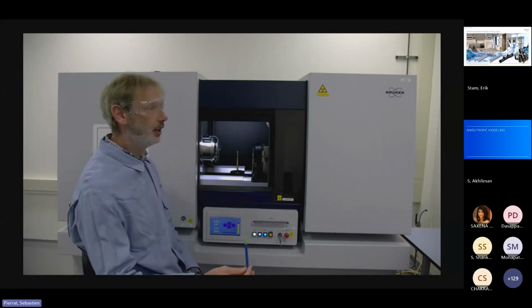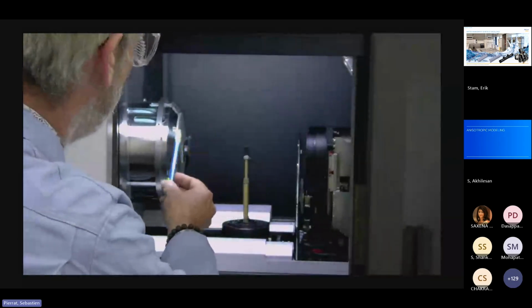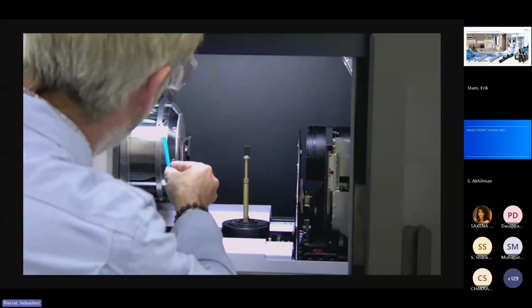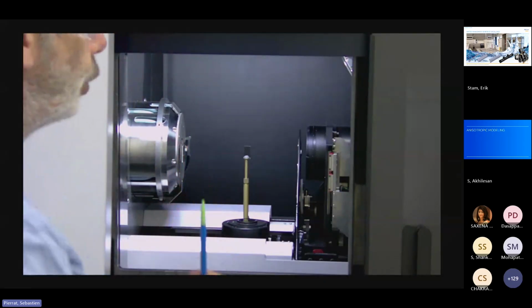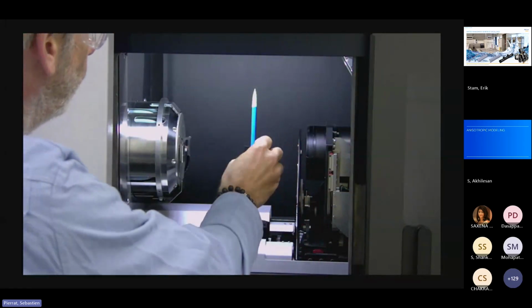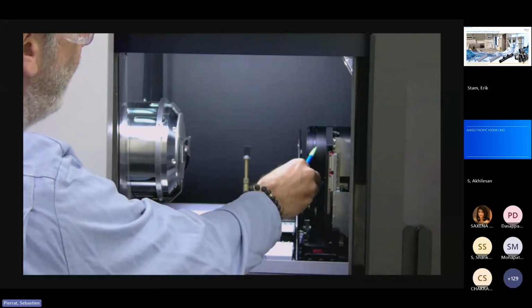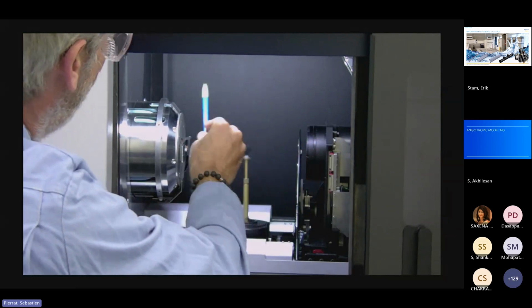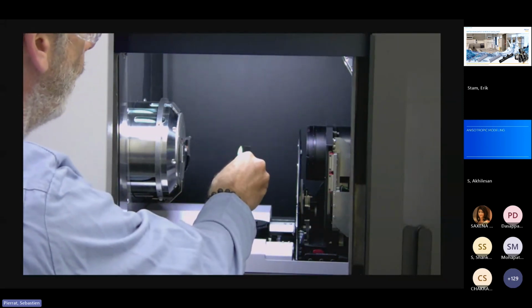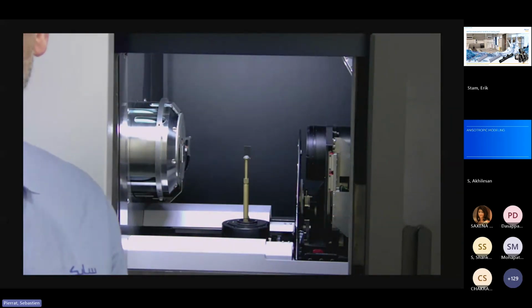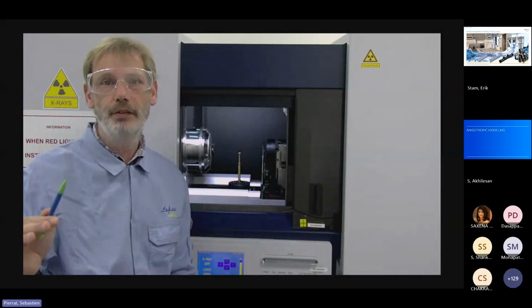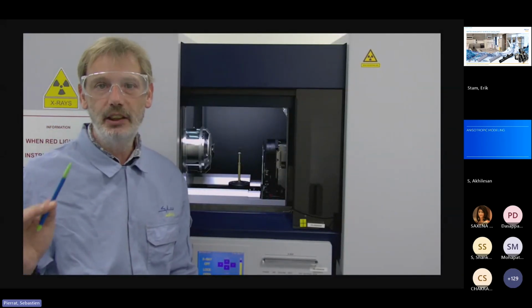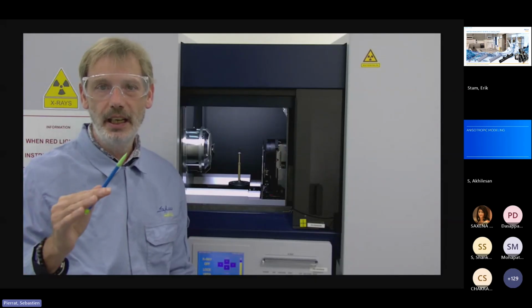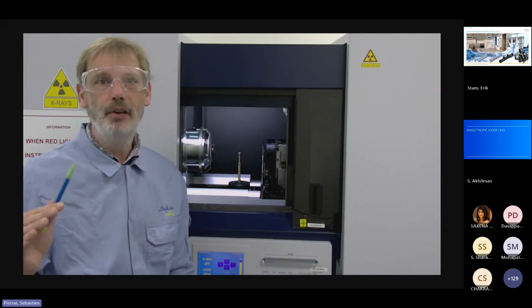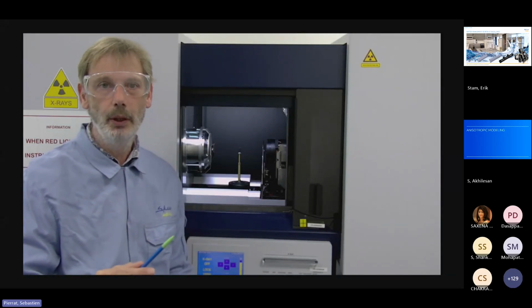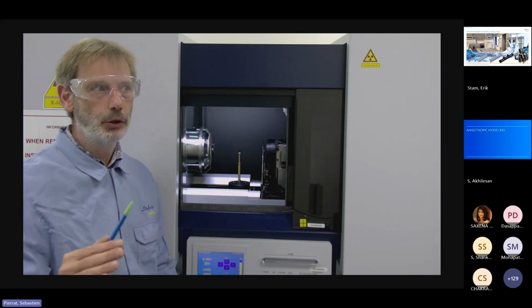The image acquisition is performed with an X-ray scanner. It contains an X-ray source, which is focused on a collimator to create a cone-shaped beam, which then irradiates the sample, and the image is acquired with a detector located opposite the source compared to the sample. The contrast which is generated depends on the attenuation of the X-ray inside the material, and the attenuation is stronger as the material is heavier. Glass fiber has a much higher density as compared to polymer. It will attenuate the X-ray much more strongly and then create a contrast.